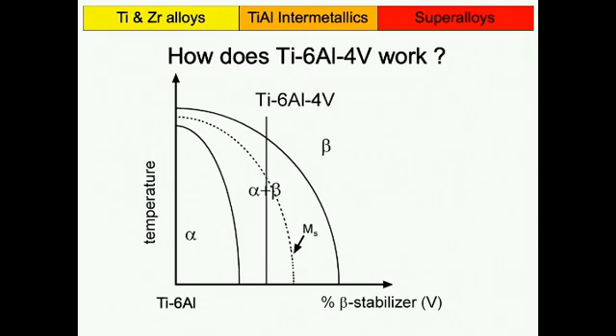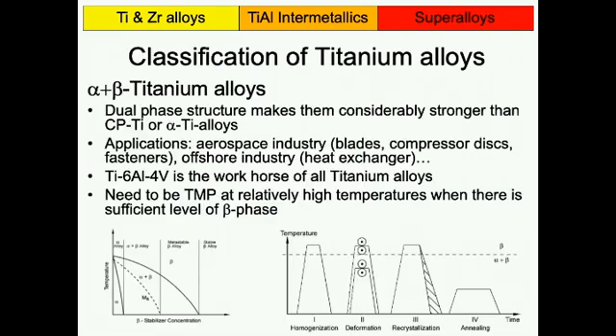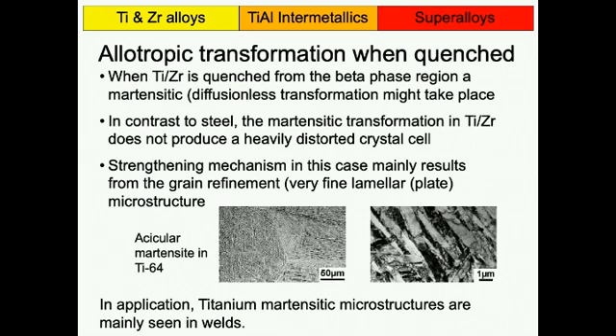If you are on the right hand side of that dashed line, if you now quench the material, you will just freeze the high temperature microstructure. So you just retain your beta phase. It's a metastable condition, so if you anneal it afterwards, it will transform. But during quenching, it will not form this fine lath structure which I've shown you here, but it will just retain the beta phase. It's a bit like retaining austenite, which can also happen in steel.